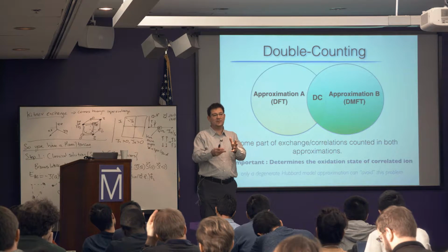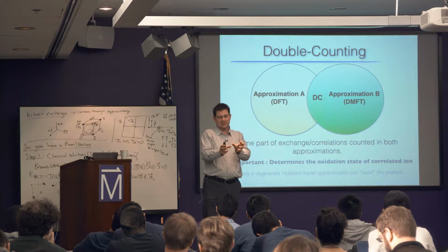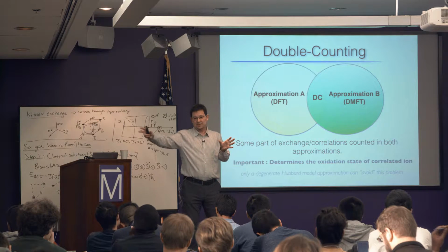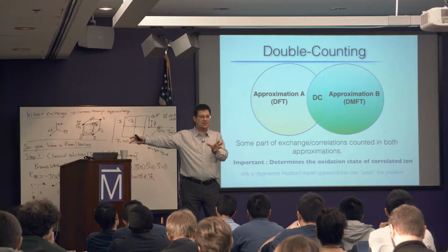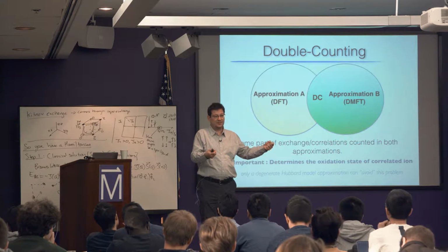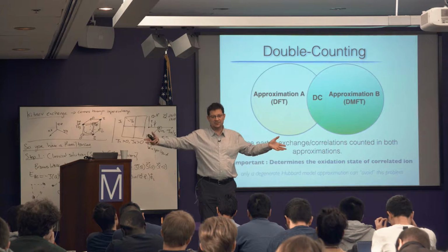When you crank up your Coulomb repulsion, what's going to happen is that the states which have large Coulomb repulsion will shift to positive frequency, because you're adding bigger and bigger Coulomb interaction. So you have to subtract some of the Coulomb interaction in order to make them centered more or less where you started.